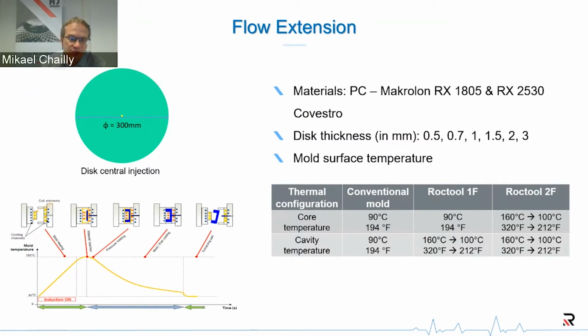Then we consider that we have implemented Roctool on one side, so on this side the temperature would start from 160 degrees C at injection start and getting down to 100 degrees whenever we demold the part. The third configuration would be to heat both sides with the Roctool system with the same temperature profile starting from 160 down to 100 degrees C.